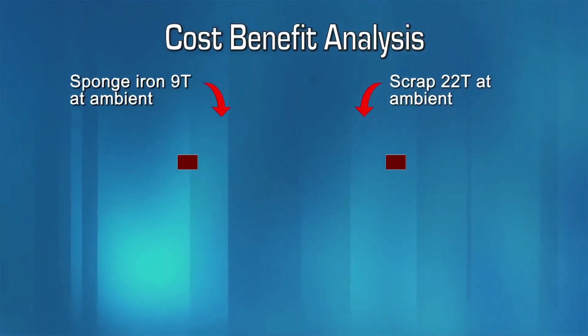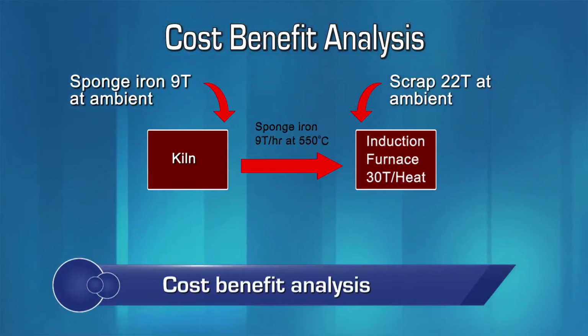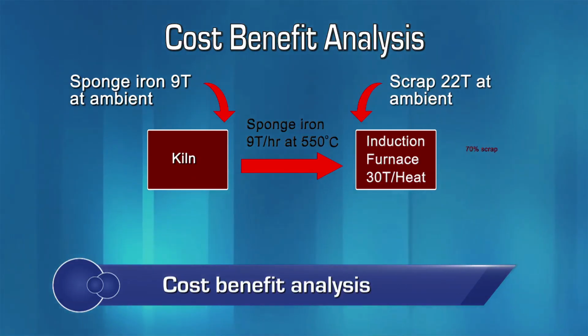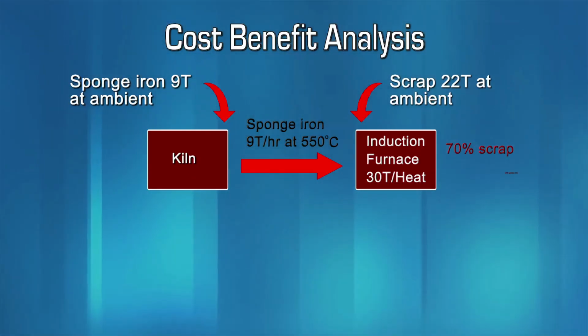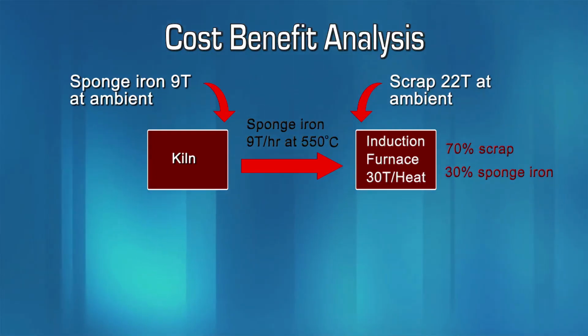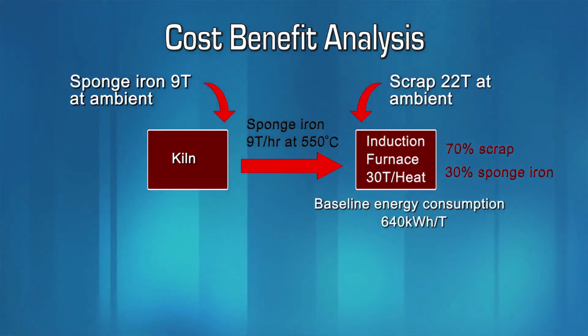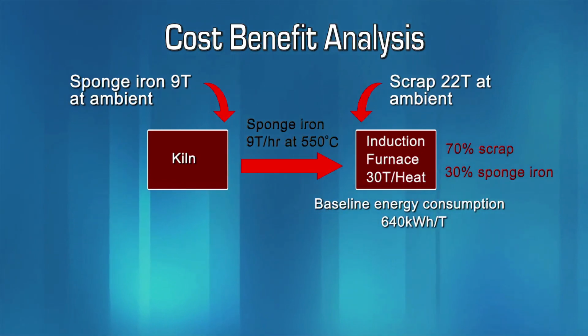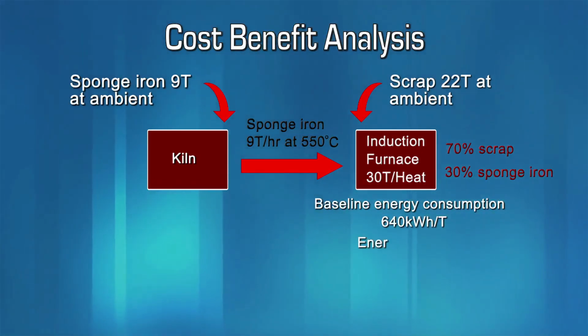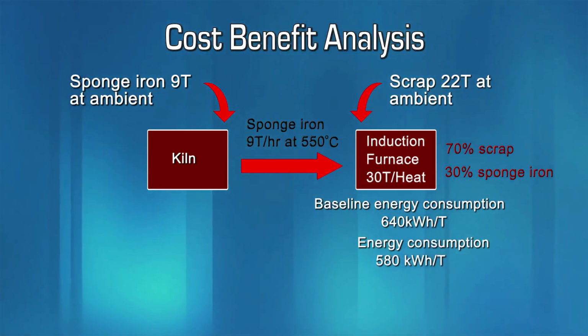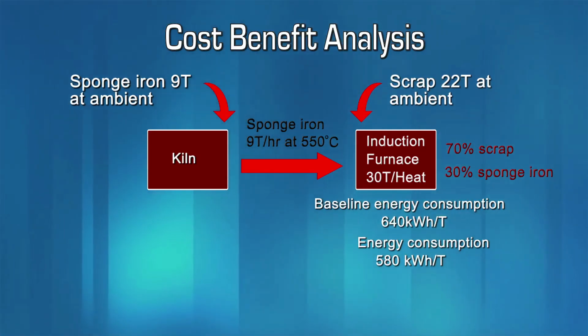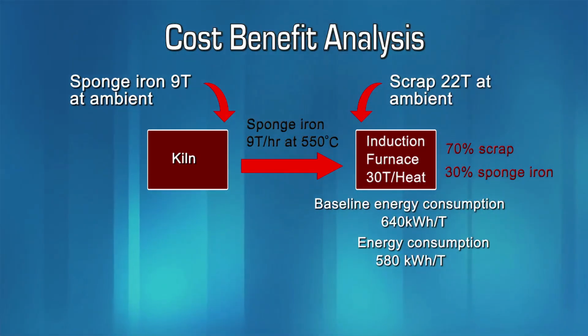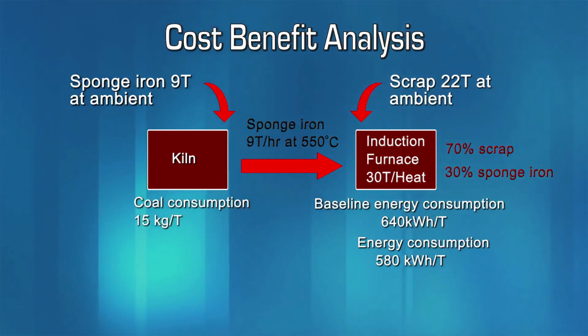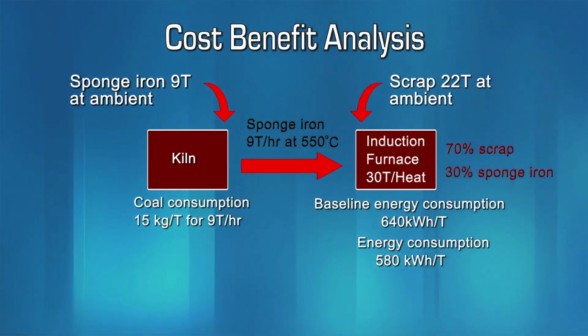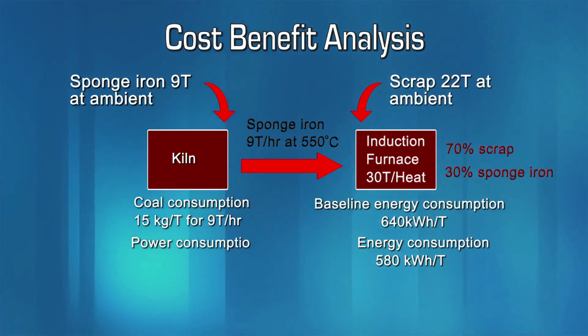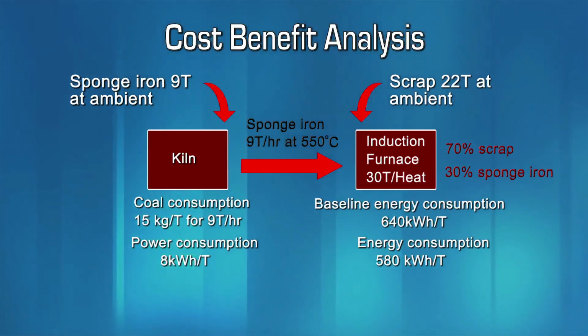To understand the cost-benefit analysis, let us consider a 30-ton induction furnace with 70% scrap feed and 30% sponge iron feed. The induction furnace has a baseline energy consumption of 640 kWh per ton. With use of preheated sponge iron, the specific energy consumption of the furnace is reduced to 580 kWh per ton. The system also uses pulverized coal at 15 kg per ton. Extra electrical consumption is 8 kWh per ton.